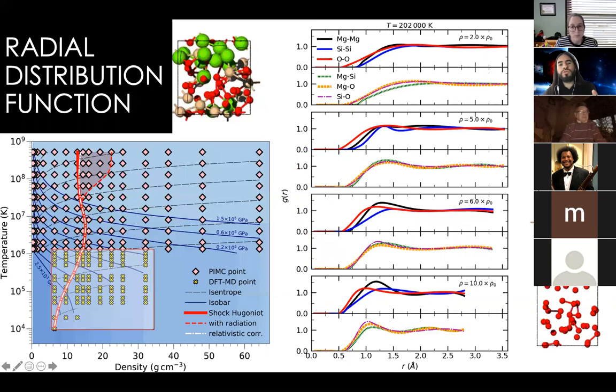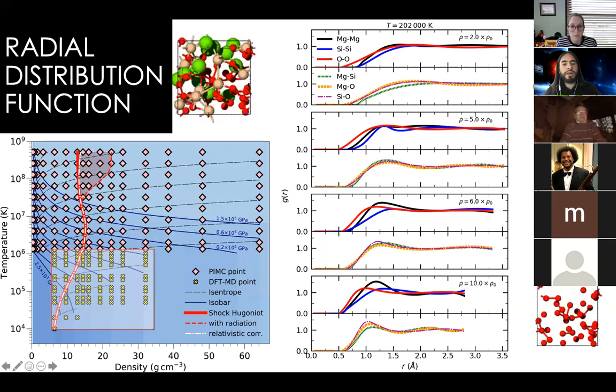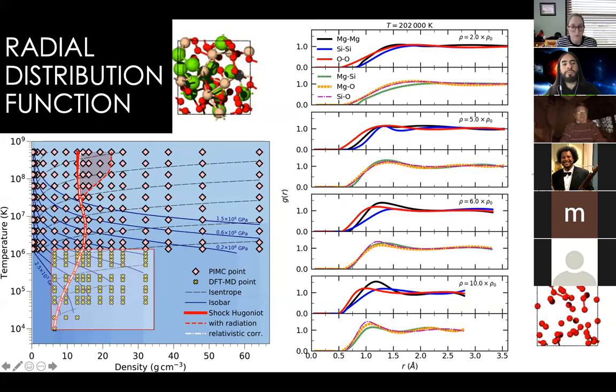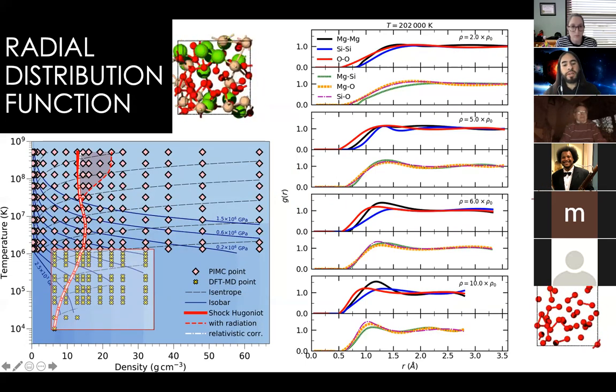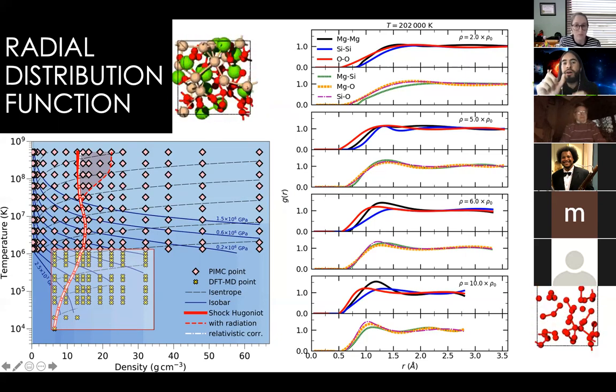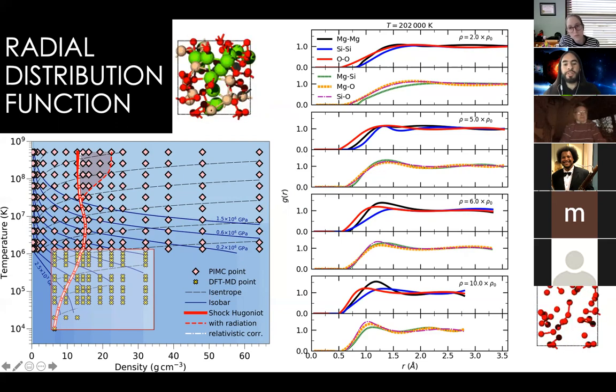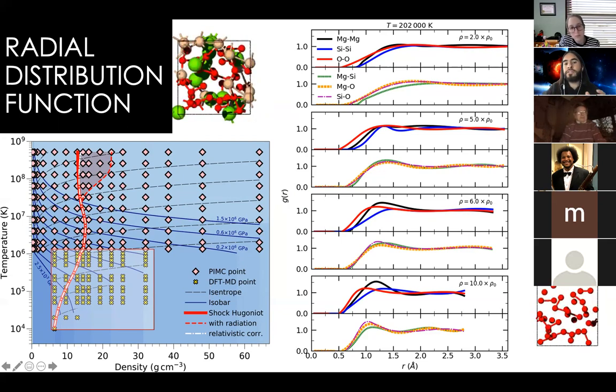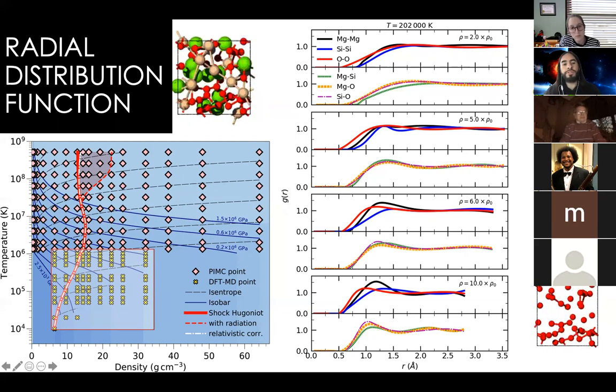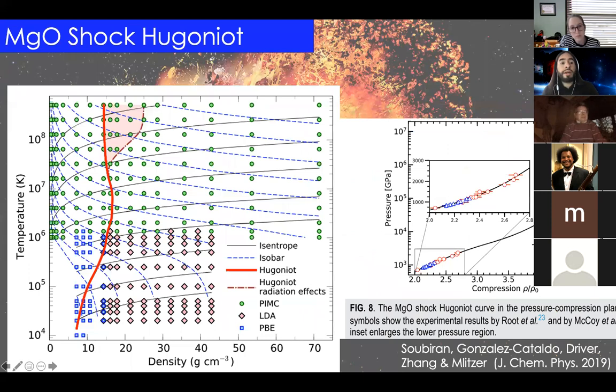So we can do all sorts of diagnostics for matter at these extreme conditions and calculate, for example, this radial distribution function, where these peaks basically tell us the average bond length, like what is the separation between different types of atoms. And you can see that they are different at different pressures, different densities, and different temperatures. When we did it for magnesium oxide, which is also a very relevant material for planetary science, we also see a very nice agreement between the available experiments at these extreme conditions and our predicted Hugoniot curve here in red. So this is very encouraging because it seems that we're doing very well.